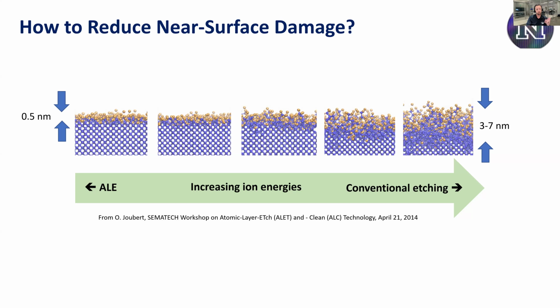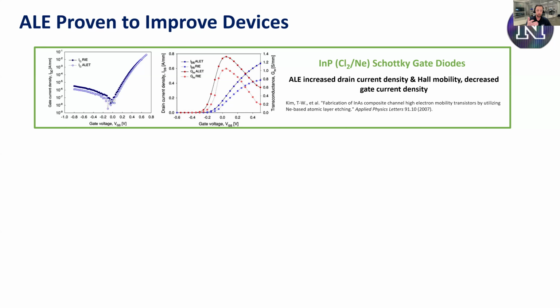This is an early example in 2007 on indium phosphide Schottky gate diodes where they use chlorine and neon actually. Usually you'll see argon, but in this case neon. And ALE was shown to increase the drain current density and Hall mobility, decrease gate current density. They saw a big performance increase. Similarly with these aluminum gallium nitride devices, Schottky barrier diodes, they're able to reduce leakage current. And I want to call your attention there to the images kind of on the lower left. You can really see this defective amorphized layer is much thinner when they use the atomic layer etch process. So that really matters for real devices.